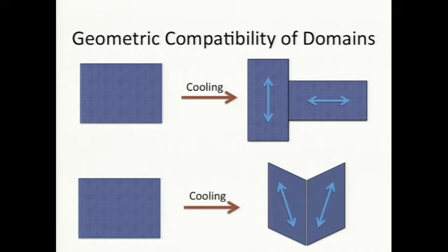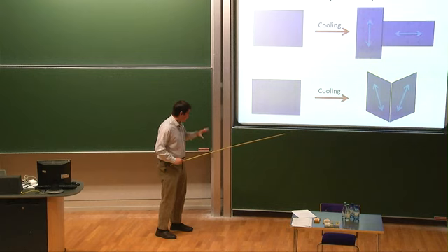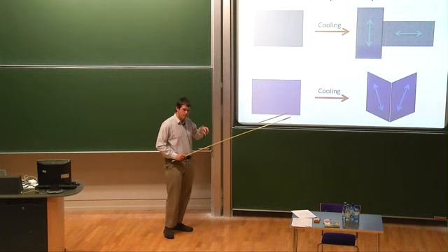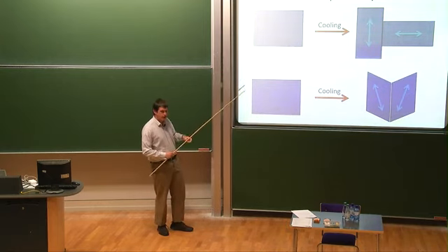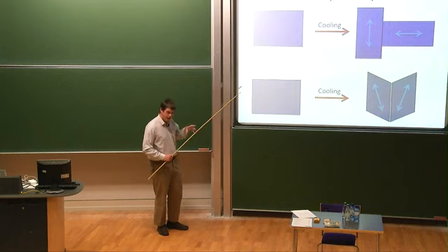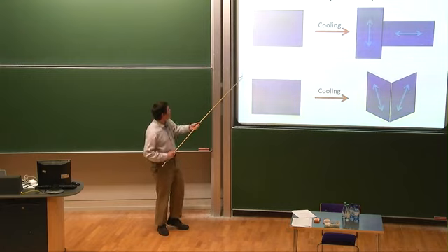And so the key insight, which I think explains why, if you cross-link in the isotropic state, you get a completely soft macroscopic response, is as follows. We're now dealing with the free energy. So the energy is minimized by a distortion of magnitude r to the 1/3 in any direction, okay? So an elongation in any direction, and then you put the liquid crystal director along that direction, which gives you an energy minimum.